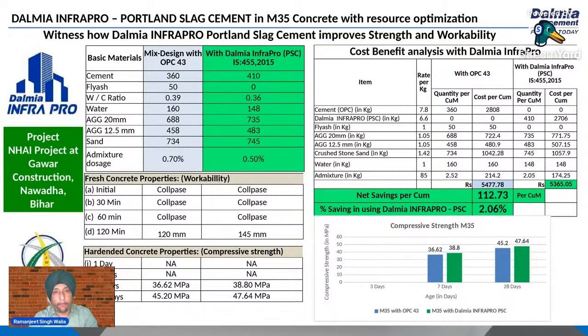This is a classic example of a highway project where OPC was mentioned in the specifications, but we approached the authorities and the contractor also. We did a lot of trials there, and they found benefits with using PSC, and now they are using it. Earlier they were using 360 kg OPC plus 50 kg fly ash, but most of my experience is in ready mix concrete, and nowadays consistent supply of GGBS or fly ash is not available in places. They were having issues in their fly ash supplies, and it was also not good quality fly ash. So we suggested they use PSC.